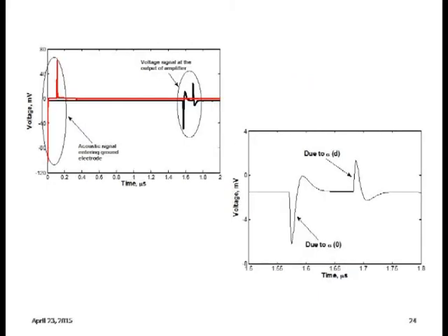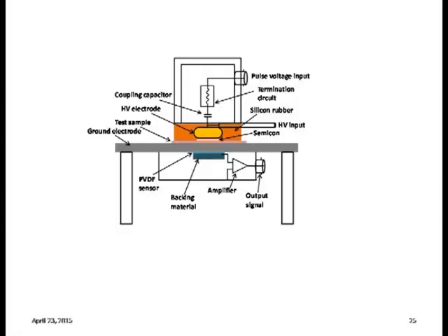Here, this is the actual signal that is generated, and this is what is reaching the transducer. After the transducer you can clearly see this type of shape distortion. This supports the already found result that the amplifier distorts the space charge result, and we found the transfer function of that amplifier and then obtained the original signal, as obtained after the simulation. So this is the electrode setup that has been developed at our institute. The block diagram is shown here.